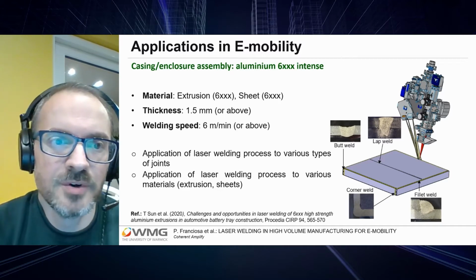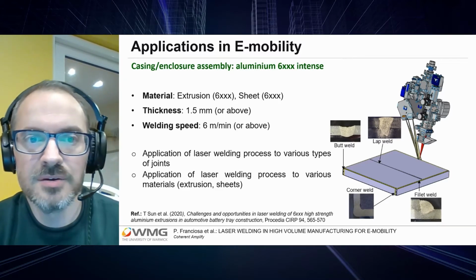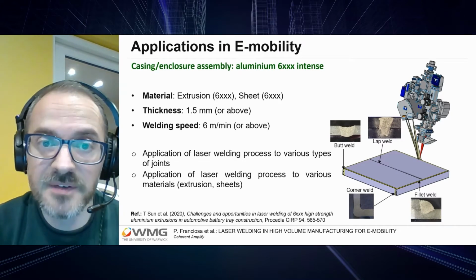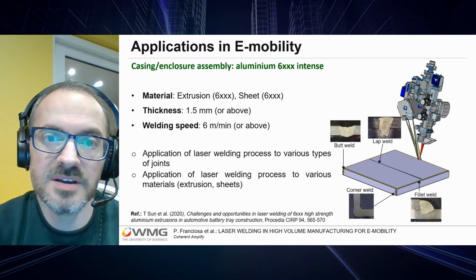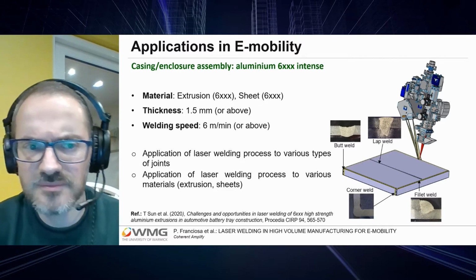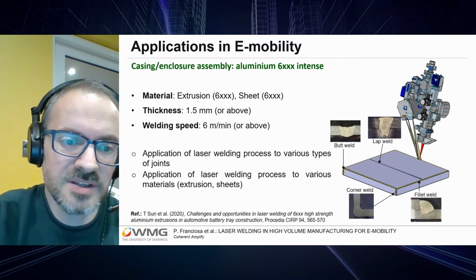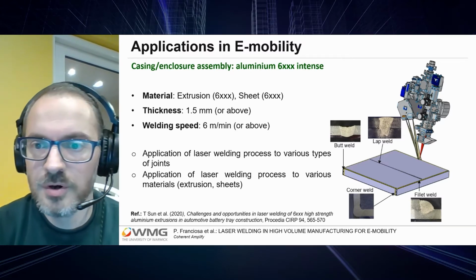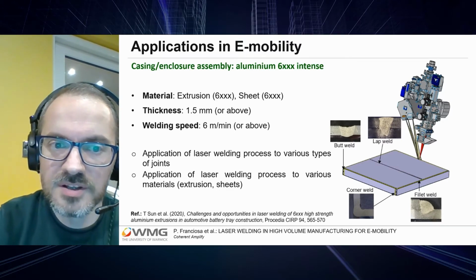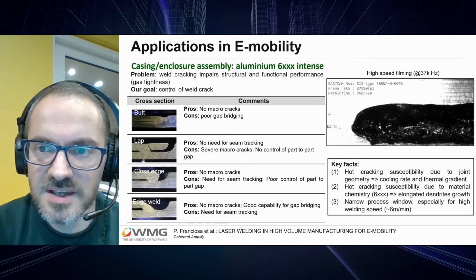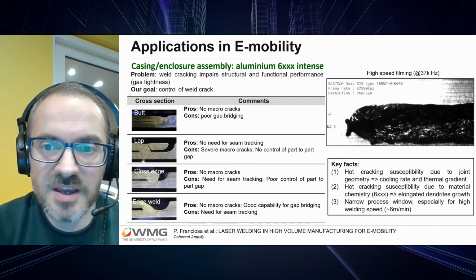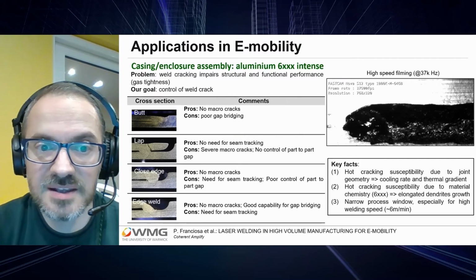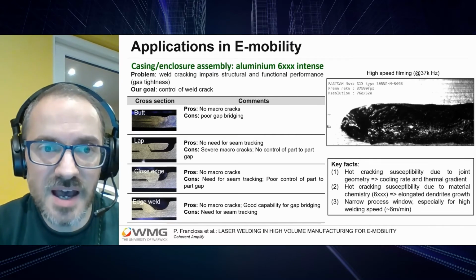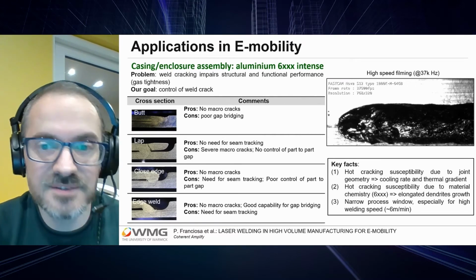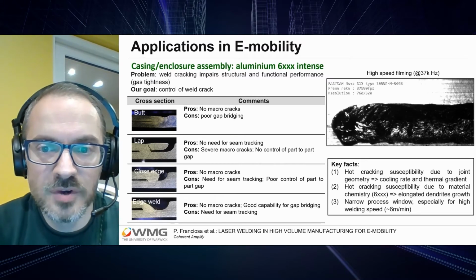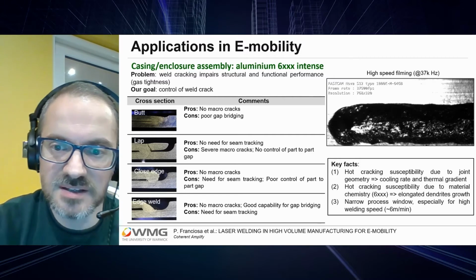The second application is more related to casing and enclosure assembly, specifically looking at construction with the high-strength aluminum 6000 series. More details can be found within the paper which I have cited at the bottom of the slide. So the overall challenge was: we know that 6000 series can be welded with filler wire, and then we can get rid of cracks and micro cracks problem. But the question is, is there an alternative to that? Can we use the ARM technology, the dual beam shaping technology, to achieve very similar results? And this is what we did.